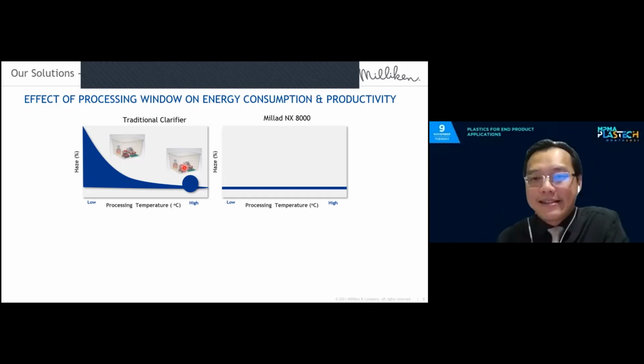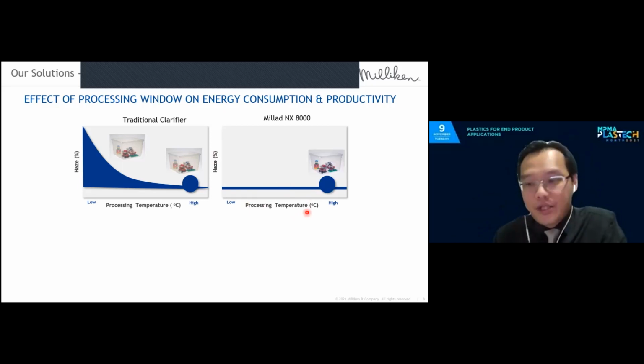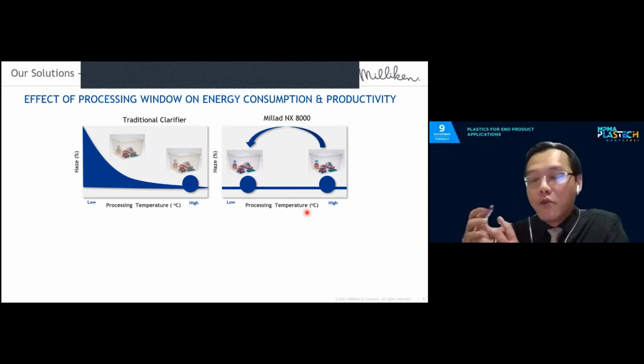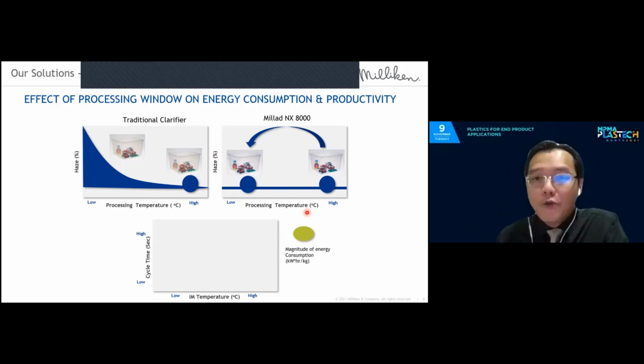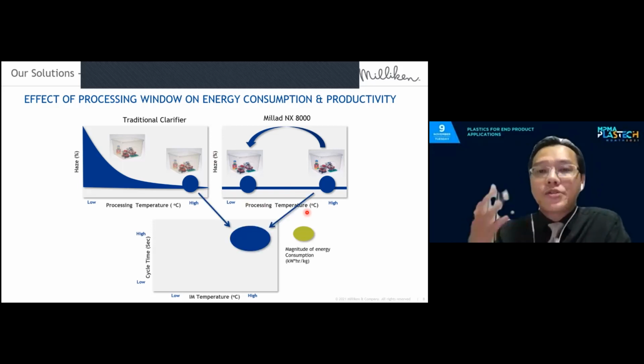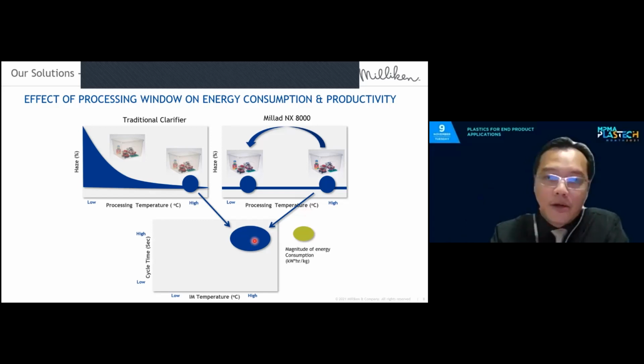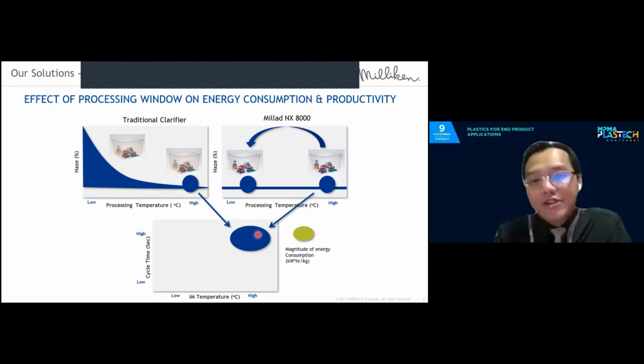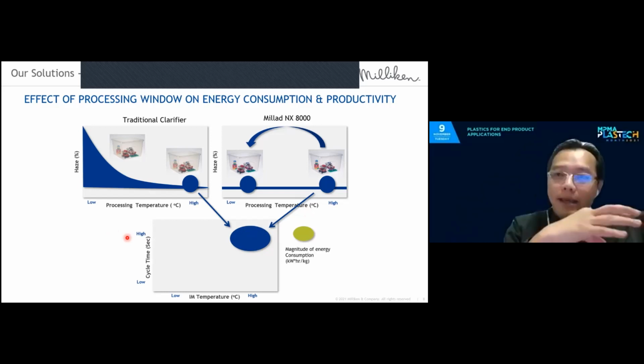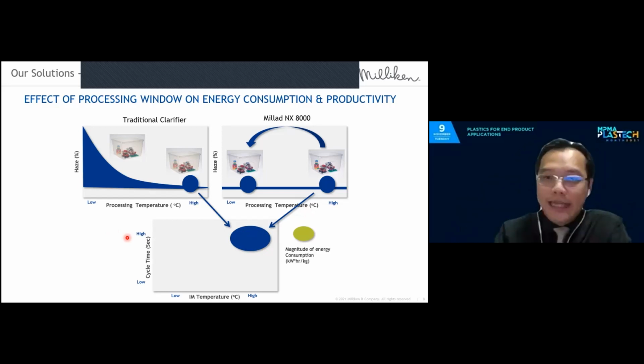But since we introduced Millad NX8000, it is insensitive, right? The haze, the optical performance is not sensitive to processing temperature. And therefore, whether you process it at a high temperature or a low temperature, it works fully, it functions properly, there is no degradation or there is no negative performance. And so we can translate that. Traditionally, the industry used to have to process clarified random copolymer injection molding at high temperatures. And naturally, if you are molding it with high melt temperature, you would also need high cycle time. The hotter your melt, the more time you need to cool down in your mold before you can eject properly. And we try to symbolize the size of the circle, the size of the bubble as a magnitude of the energy consumption used.